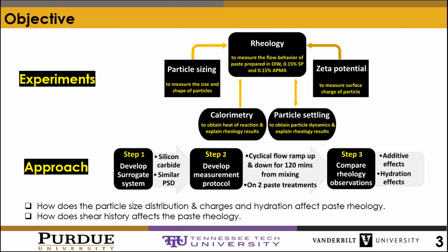We chose silicon carbide as the material because it is eminently inert, and compare it to cement particles. And we made sure that the particle size distribution, at least for some base conditions, were the same. The reason why I'm using silicon carbide is because I'm trying to isolate the factors that affect rheology. And I want to know how much of a factor hydration is in the first 120 minutes under shear conditions. So I'm trying to understand the effect of additives on rheology and how much of rheology under flow conditions is contributed by hydration and how much is particulate driven.